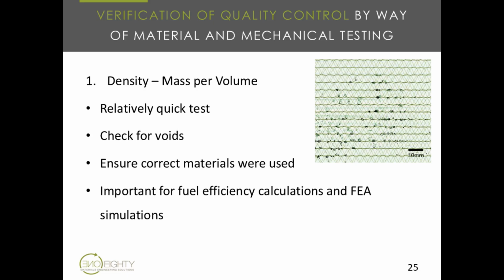So during manufacturing, was the resin completely devoid of air particles or air molecules during the curing process? You're also checking that the correct materials were used during the manufacturing process, and that ties into compliance as well, because when you're audited, they will make sure that the materials you listed, the expected density, that you are meeting that after manufacturing. And like I said earlier, it's important for fuel efficiency calculations, but also FEA simulations.